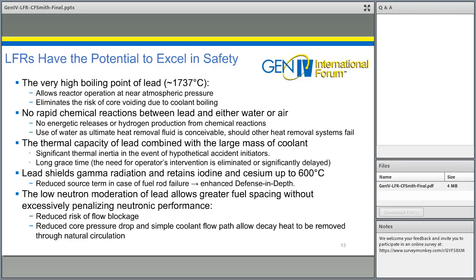an upset condition. Next, lead is an effective shield against gamma radiation, and it retains iodine and cesium, as well as other radionuclides at temperatures up to 600 degrees centigrade or higher. This results in a significantly reduced potential source term in case of fuel failure and contributes to enhanced defense in depth. Finally, the low neutron moderation of lead allows greater fuel spacing without excessively penalizing neutronic performance. This results in reduced risk of flow blockage and reduced core pressure drop while enabling a simple coolant flow path to allow operational and decay heat to be removed through natural circulation.